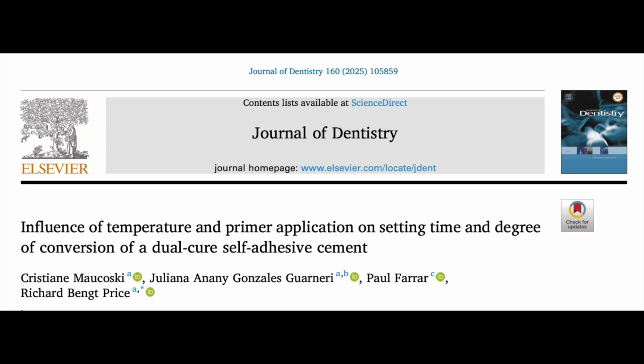Interesting. Okay, let's talk heat. Temperature during the curing. Yes, they tracked that too. And the main source of temperature rise wasn't actually the cement's own chemical reaction, the exothermic part. It was the curing light. Overwhelmingly so. The light curing unit caused temperature increases of up to 46 degrees Celsius. Wow, that's substantial. It really is. The cement's own reaction only added about 9 degrees C on top of that. And while they didn't directly study pulp effects, that kind of heat certainly makes you think about potential sensitivity, doesn't it? Absolutely. It underscores being mindful of the heat generated by powerful curing lights.